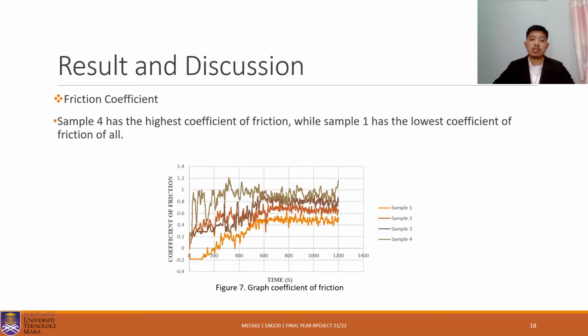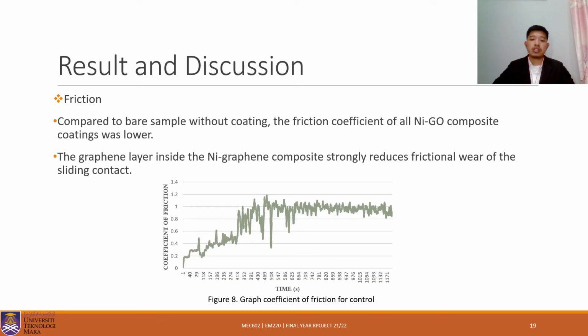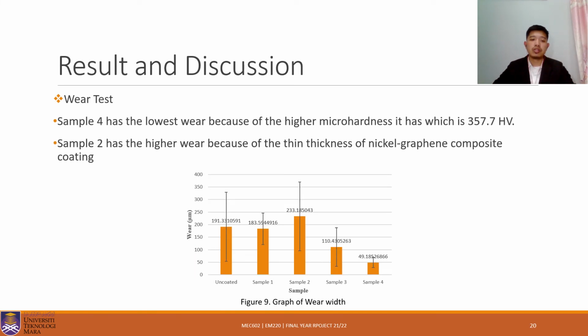Friction coefficient. Sample 4 has the highest coefficient of friction, while sample 1 has the lowest coefficient of friction of all, as shown in figure 7. Compared to the bare sample without coating, the friction coefficient of all nickel graphene oxide composite coatings was lower, as shown in figure 8. The graphene layer inside the nickel graphene composite strongly reduced friction of the sliding contact. And lastly, for wear test, sample 4 has the lowest wear because of the higher micro hardness it has, which is 357.7 HV, while sample 2 has the higher wear because of the thin thickness of nickel graphene composite coating, as shown in figure 9.